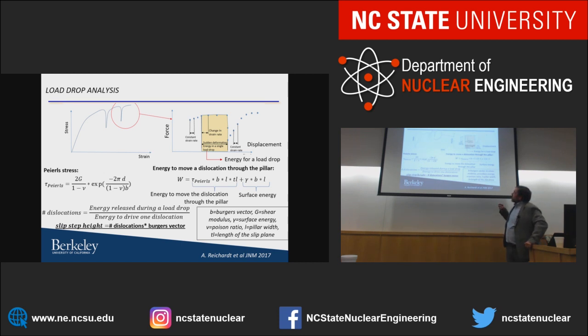And so we do that and calculate the area underneath the force displacement curve, which gives us the energy in that event. And so that we put in correlation with the energy it takes to drive dislocations through this structure. And so we calculate the Peierls stress, which is the stress it takes to drive a dislocation. The Peierls stress times the dimension of the pillar plus whatever surface energy term you're going to create. You put the measured energy in correlation to the energy it should take to drive one dislocation through. That gives you the number of dislocations participating in the event. And then the number of dislocations times the Burgers vector gives you the slip step height. And if you do that, then you come up with numbers.